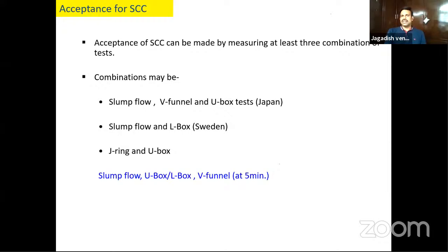And we actually suggest slump flow, and either U-box or L-box. And you can measure the V-funnel at 5 minutes. That also gives a very good indication of the segregation resistance.